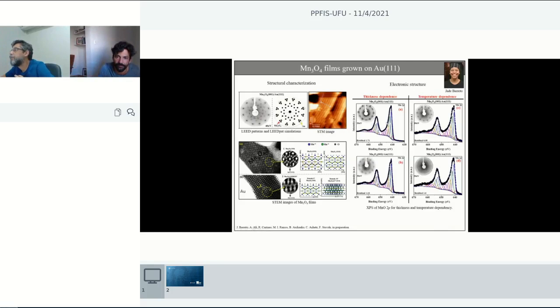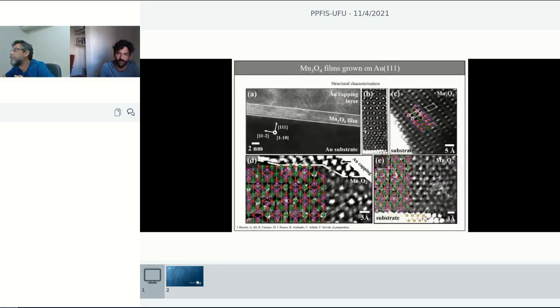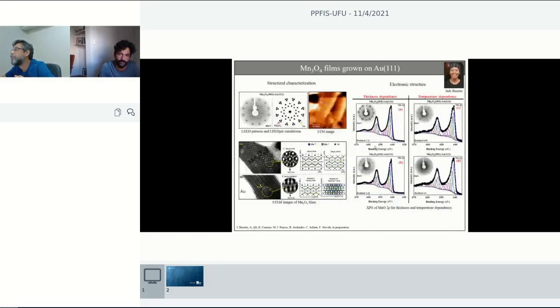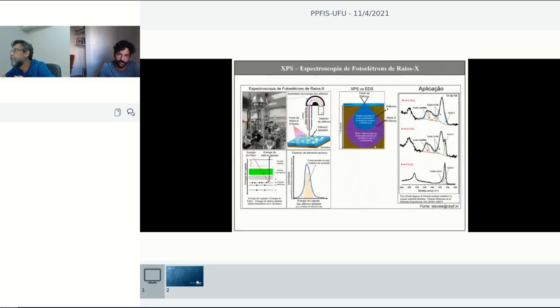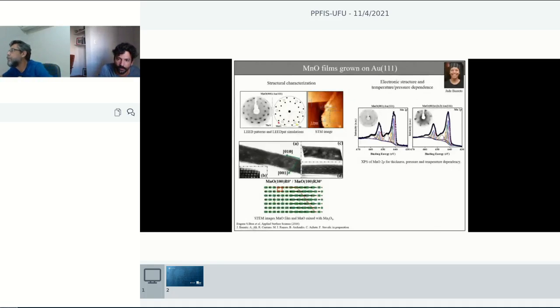This is the 3/2, this 1/2, this spin-orbit splitting. And then depending on the shape, look at the shape of the Mn3O4, compare it to MnO. So you see that there is a satellite structure here. The distance of the satellites is different to the other one. So the shape changes here. So you get a lot of information there. That's why you look to the 2p peaks.